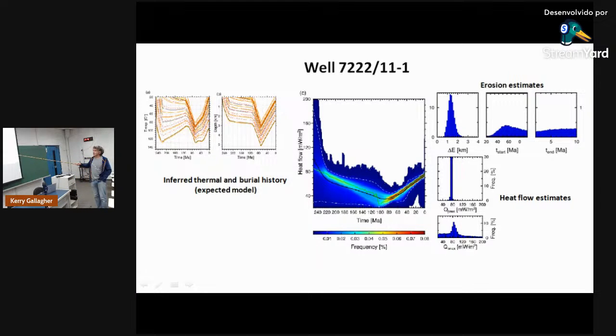So remember, that's how we can calculate temperature. And again, we didn't know the duration of this unconformity, when erosion starts, how much was missing. We didn't know that in advance. It's something we estimate, again, around 1.5, nearly 2 kilometers. We get the timing, start of erosion, sort of this time, and the end of erosion. And here we're just showing one model. In fact, it's the model based on this black curve here. But clearly there's uncertainty in this timing. There's uncertainty in the magnitude of this erosion. But we quantify that with this approach because it's Bayesian and we get posteriors on everything.